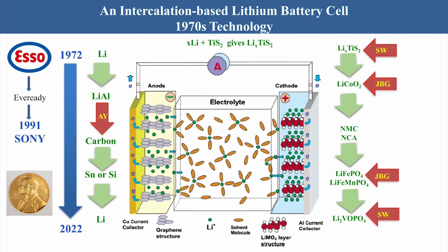On the cathode side, we worked on the layered compound lithium titanium disulfide. It worked very well, but the energy density wasn't all that high. John Goodenough, who was at Oxford at the time, working on the magnetic behavior of lithium cobalt oxide, said, hey, these two structures are the same. Let's see if cobalt oxide will work. Well, no self-respecting chemist would look at lithium cobalt oxide. Cobalt-4 doesn't exist according to chemistry textbooks. But John was a physicist. He said, I'm going to try it, and the rest is history.